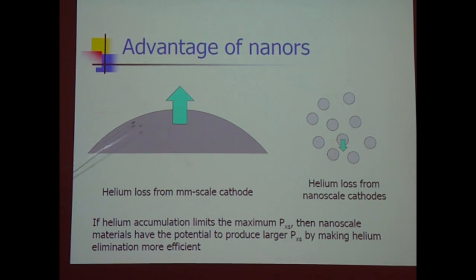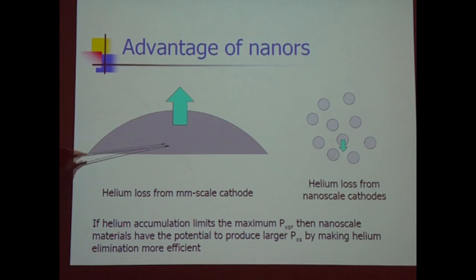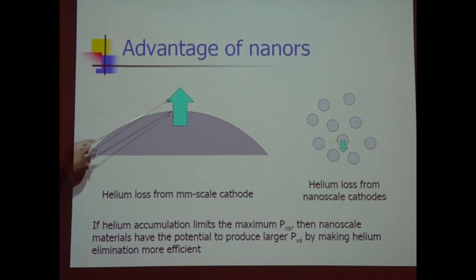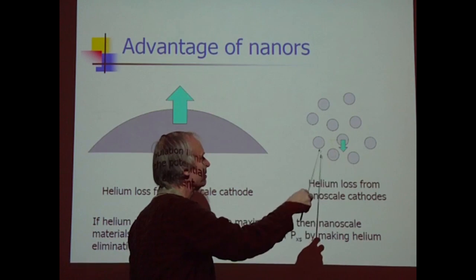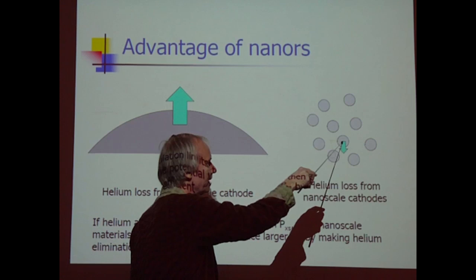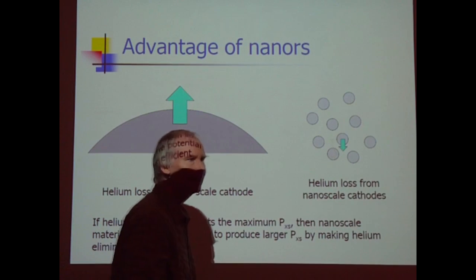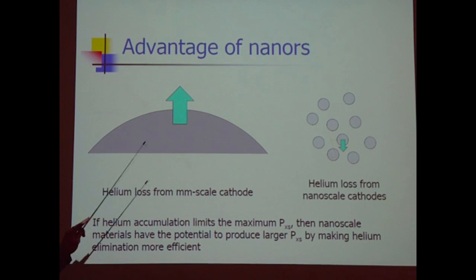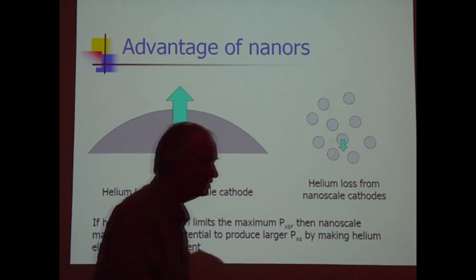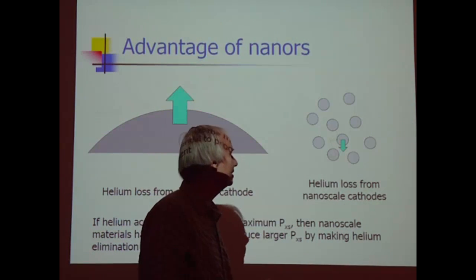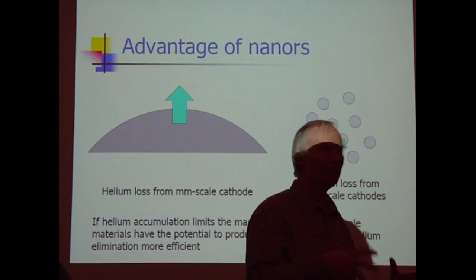So the idea is that you've got a big cathode. If your excess heat is made inside here, your helium has got to go a long way to reach the surface. But if you've got nanoscale palladium in a matrix of some sort, and your helium goes from the site where it's produced a small distance to your matrix, and if your matrix is capable of communicating it elsewhere, then this system has the possibility of running at much higher power density than this system. So an interesting experiment would be to test the temperature dependence of a nanoscale system, and also see if the excess power scales in a way consistent with diffusion as a function of nanoparticle size.